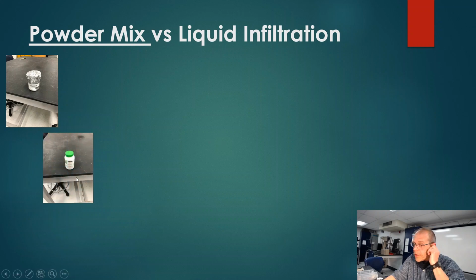We're going to use a material called polyvinyl alcohol. And why we add just a little trace amount of this is because the alumina is very, very fragile. It's kind of like making a snowball with dry snow. It's not going to clump together. You add a little water to it, it sticks a little better. You can kind of think of the polyvinyl alcohol as that water. It's a good bonding agent.